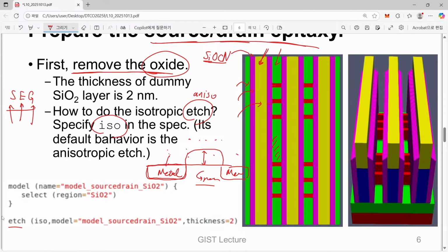Especially we will use this technique for silicon growth on top of silicon. So only where we have silicon is silicon grown. On top of silicon nitride and silicon dioxide, they don't grow.